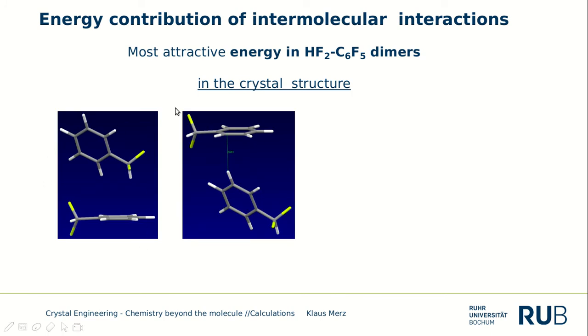These two motifs, dimers, show the highest energy of all dimers. Here are the values, roughly -4 and roughly -3.5 kilocalories per mole.